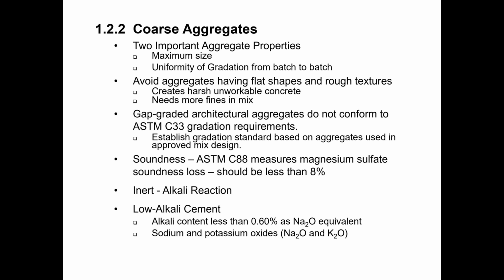All right, so if you have an aggregate that is potentially reactive, this is one step that you can take to help mitigate that risk of reactivity. Ideally, you would just not use the potentially reactive aggregate. Sometimes that's not an option. You have to use a potentially reactive aggregate. And so in those cases, definitely a low alkali cement should be used.